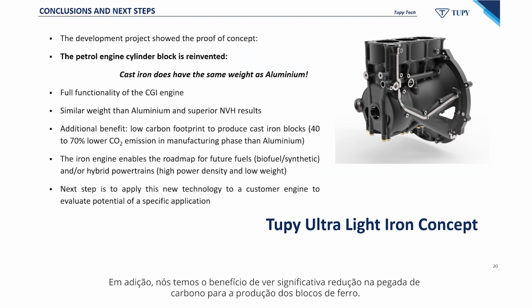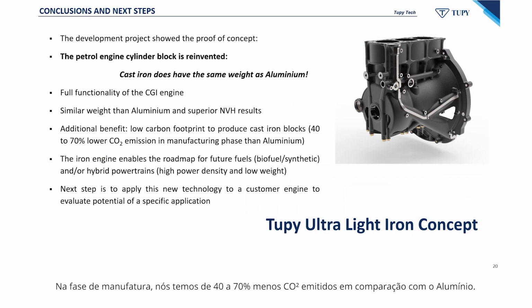In addition, we have the benefit that we see a significant carbon footprint reduction to produce the iron blocks. In the manufacturing phase, we have 40 to 70% lower CO2 emissions in comparison to aluminium.